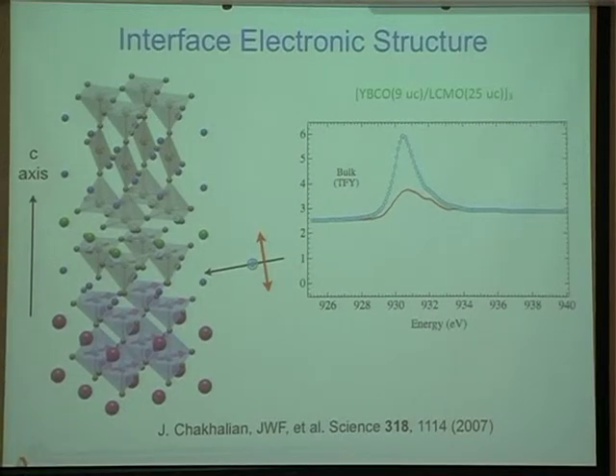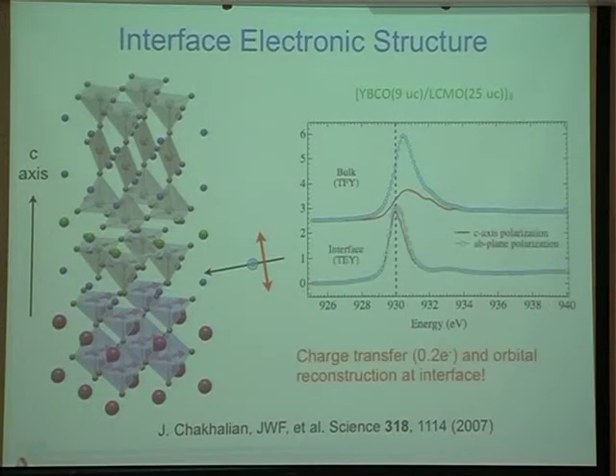But then the question is, what happens at the interface? Now at the interface, I have a manganese coupled via this oxygen to this cuprate, to this copper-oxygen plane, where all of this action is occurring. And what we found was, if you go to an interface-sensitive mode, the orbital polarization was largely killed out. We seem to have some level of occupancy in both layers. And there was a shift as well, indicating some level of charge transfer between the materials.